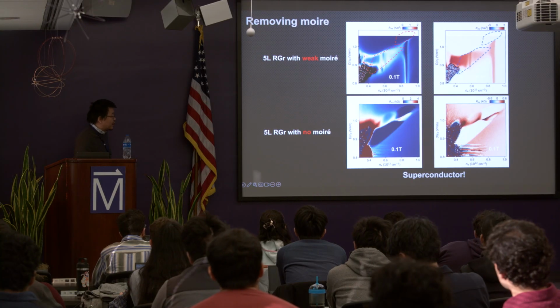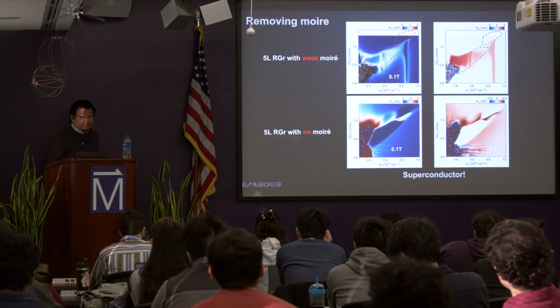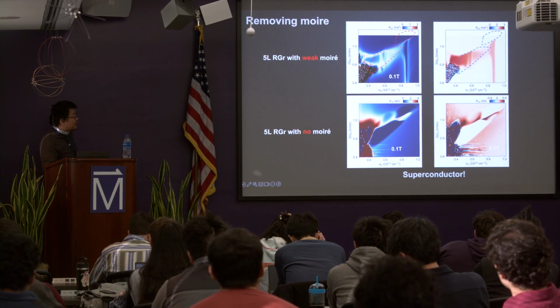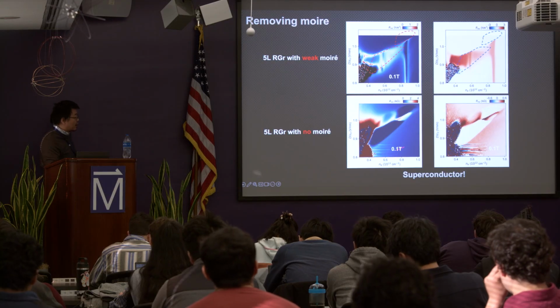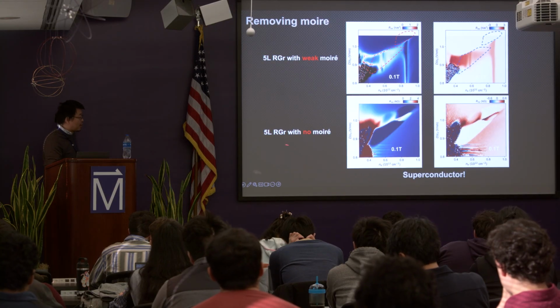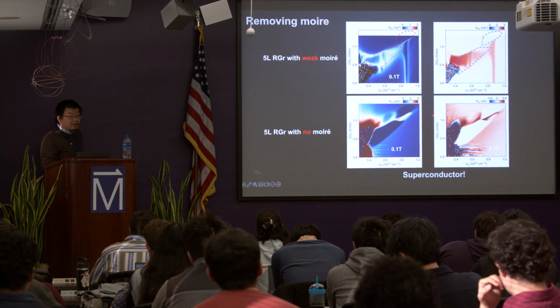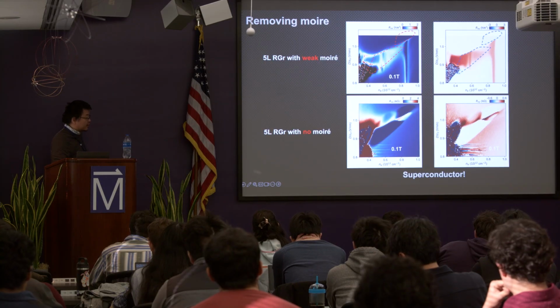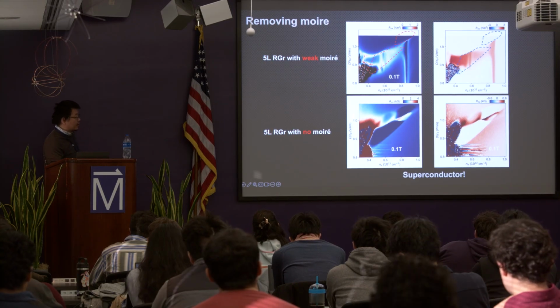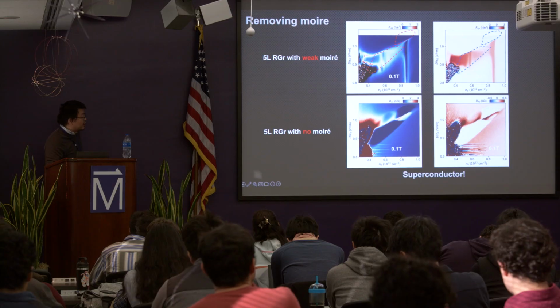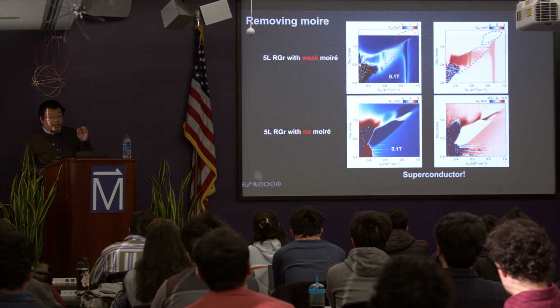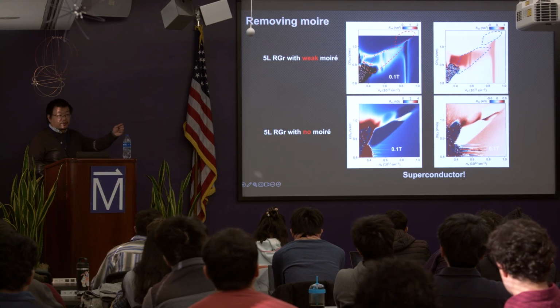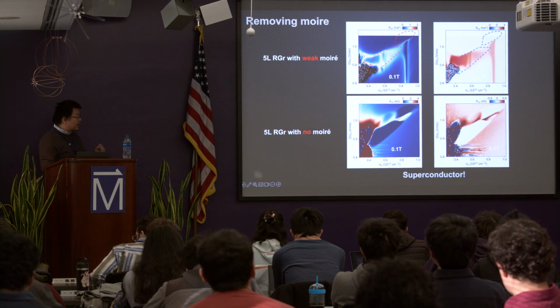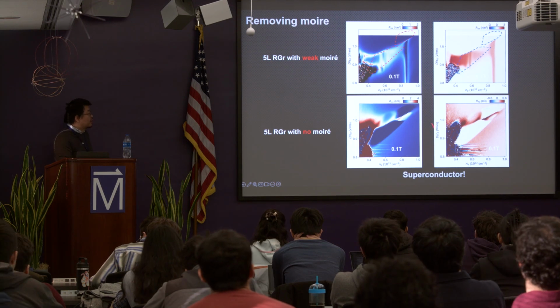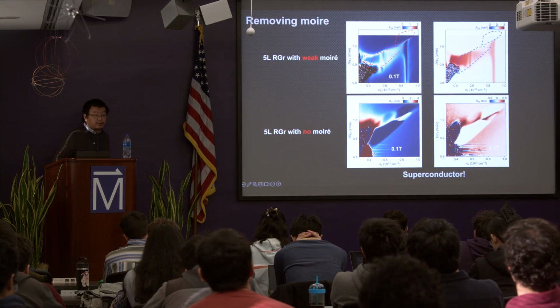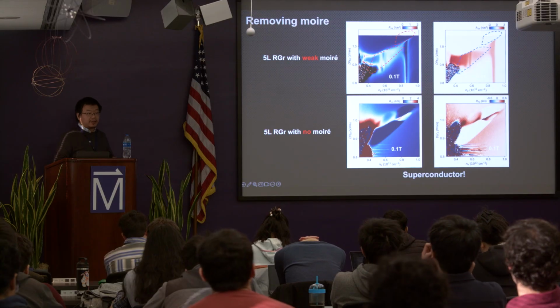And again, I want to emphasize, in terms of the phase space, if you look at what you get for the 5-layer rhombohedral graphene with and without moire, if you plot it in terms of exactly the same density and electric field, you will see that by adding this very weak moire that is remotely, like 5 layers away from the electron, you can turn a superconductivity state into a fractional quantum Hall state just by adding this very weak moire potential.